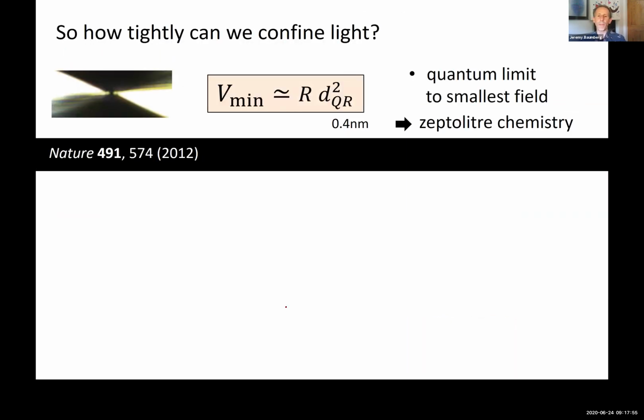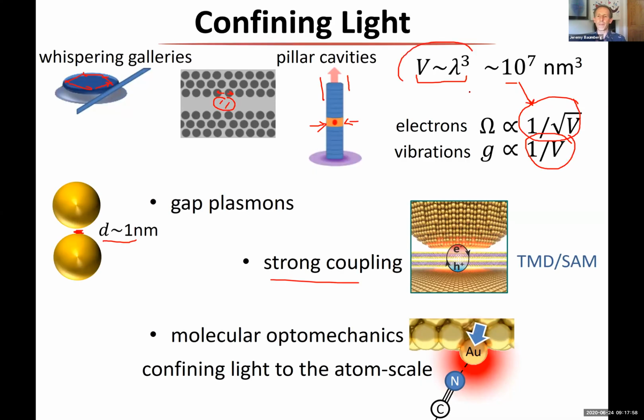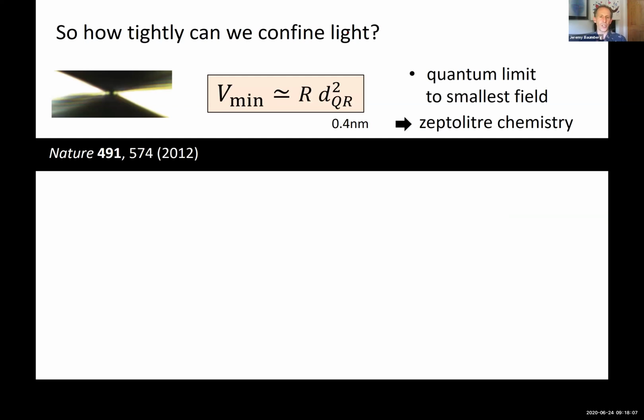So we can go back to here, and we saw that the sort of fundamental for a dielectric system is we can confine light to on the order of the wavelength cubed inside the material. If I go to a metallic system, it turns out that changes. And a few years ago, we showed by actually taking 2 nanoparticles here. So these are 2 gold nanoparticles on the end of conducting tips. And we could look optically and electrically at the same time at these. And what we could prove in the end was that as you bring these close together, in the end, you get quantum mechanical tunneling. So an electron on one nanoparticle can jump through the space in between them even before they touch. And because it does that, it shorts out the gap between them.